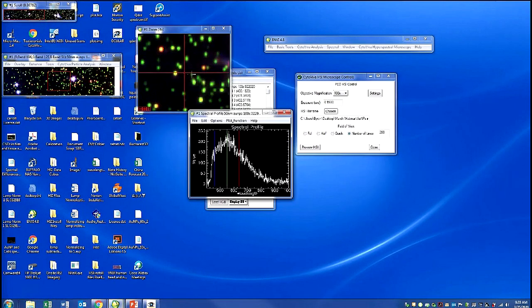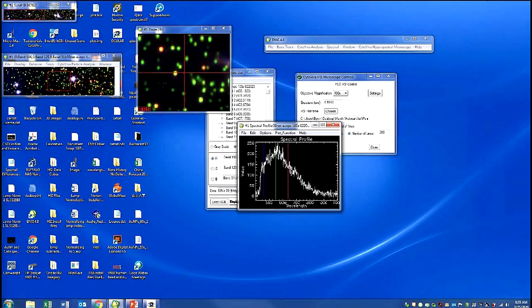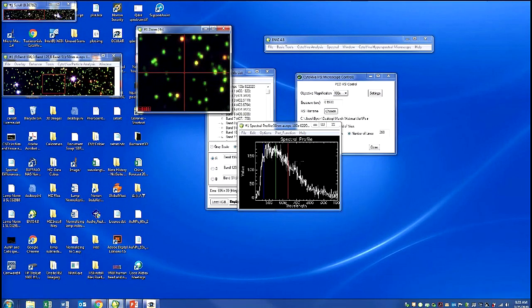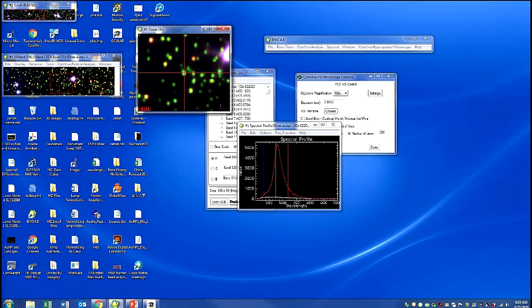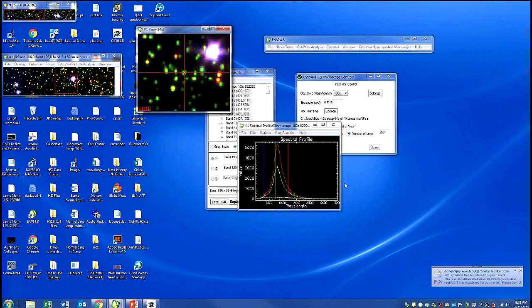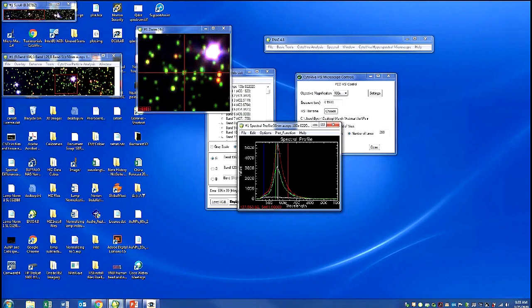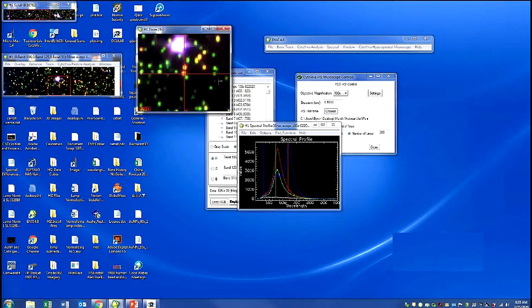But this is an actual hyperspectral image of 50 nanometer gold particles in solution on a microscope slide. As we right-click and go to that Z-axis profile spectrum again, we're off into space here, and we see just noise because we're not on an area of nanoparticles. But as we come up here on a gold particle, you see a very strong plasmonic peak with a very narrow full width half maximum, which again is indicative of the optical spectrum of a gold nanoparticle. You see the spectrum here, very homogeneous in terms of its peak, with some differences in the amplitude, maybe a factor of the focus again.